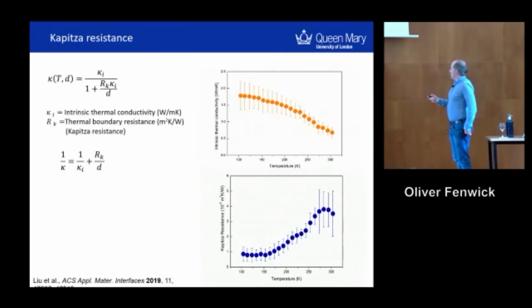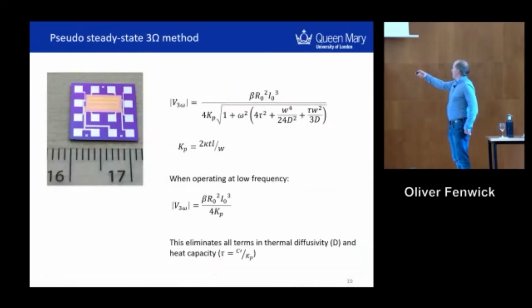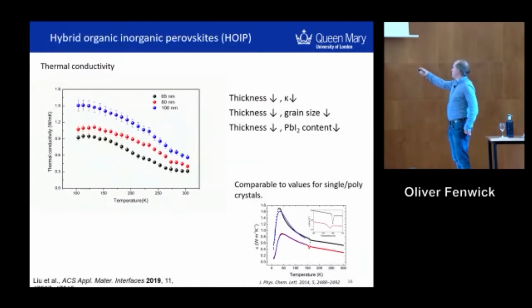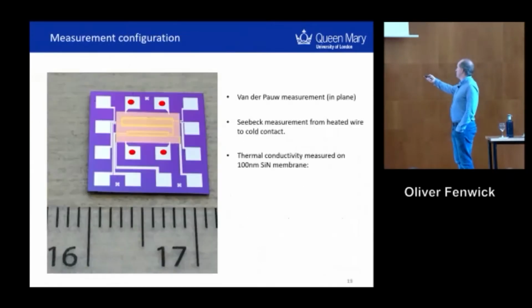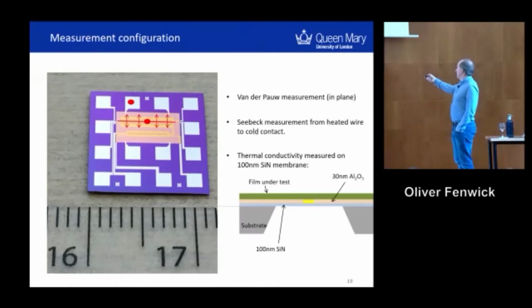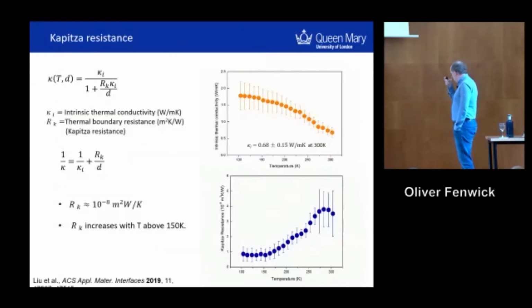That's why it's low overall, but if we look back to the original data, it decreases with thickness. And this is not thin enough to be an effect of boundary scattering in the film. So what's going on here? Well, we need to bear in mind this is a polycrystalline film, so it's not a single crystal like the first data I showed you. So there are grain boundaries in the film. And what we wanted to do is see what is the magnitude of the thermal resistance at those grain boundaries. And so we went to this equation for the Kapitza resistance, the thermal boundary resistance.